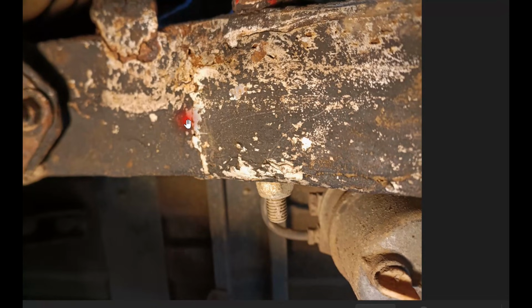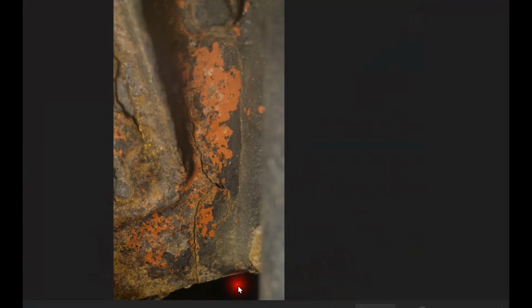And at the end here, there's a rather poorly performed fillet weld, and this has acted as a stress raiser, and a crack has formed somewhere around here. It's gone through thickness, and although it's a bit difficult to make it out, it's propagated out sideways and it's gone round the corner. Now, much easier to follow it. It's gone round the corner here. It's going up through the base metal of the web, and in fairly short order that will reach the top and you're going to have a complete failure. And this is very typical of the way that these chassis members fail in fatigue.